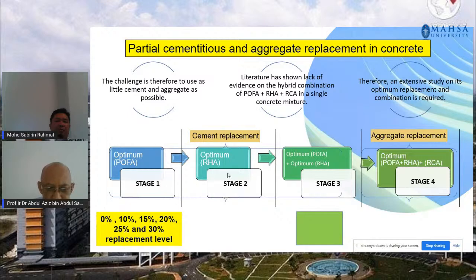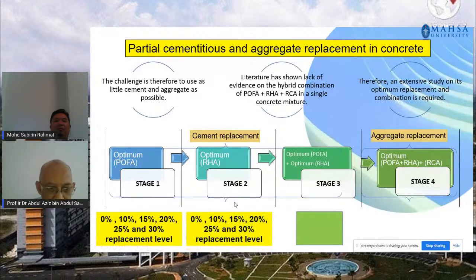And then for stage 2, I will only be focusing on rice-husk ash as cement replacement. No other waste material will be used in this study. And in this study also, I will be using replacement percentages between 10% up to 30%, as you can see on the screen now. Once I've completed stage 1, I will obtain the optimum percentage of POFA. And once I've completed stage 2, I will achieve the optimum percentage for rice-husk ash. And from there, I will do a combination in stage 3, between the optimum palm oil fuel ash and the optimum rice-husk ash.